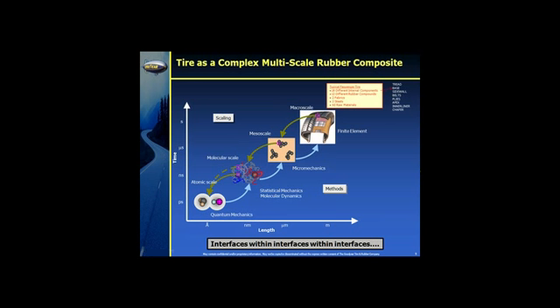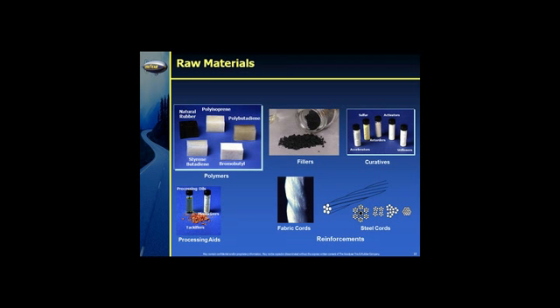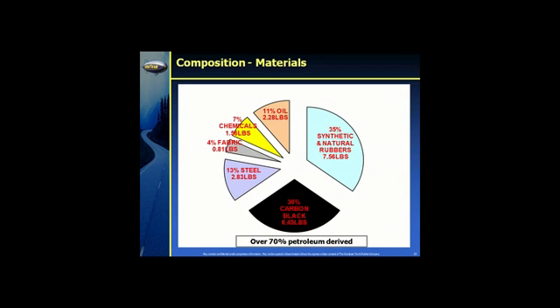So looking a little more closely into raw materials, many of these raw materials you recognize. They're drawn from a range of materials that are commodities these days: polymers, fillers. The principal filler that we use in the modern tire is, of course, carbon black, which is why tires are black, and larger and larger amounts of silica functionalized to work with rubber, curative materials, and then structurally reinforcing materials, steel cords or fiber cords like polyester and nylon, and processing aids to facilitate our manufacturing. About 70% of our materials are petroleum-based. So alternatives to this are a great challenge for us.